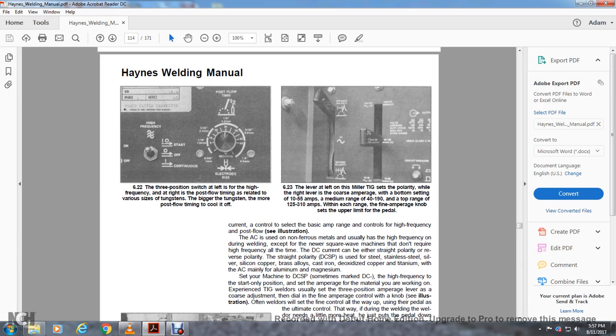In figure 623, the left lever of the Miller TIG setup is for polarity, while the right lever is the amperage range: the bottom setting is 10 to 55 amps, the medium range is 40 to 190 amps, and the top range is 125 to 310 amps, with each range having a fine amperage knob setting up to the upper limit of the pedal.